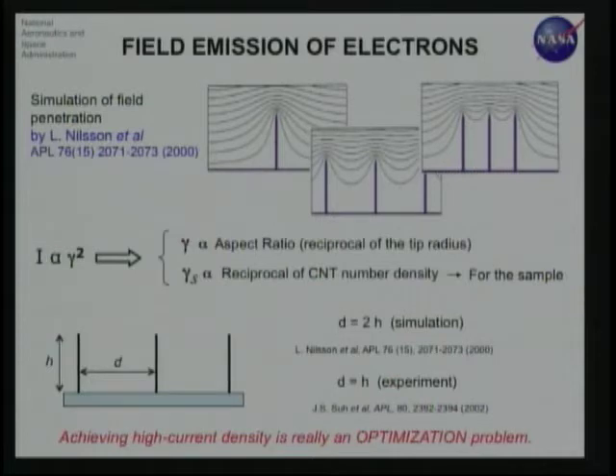And that is done by different ways. One of the ways identified is if you keep the distance between two consecutive emitters to be twice the height of the emitter itself, then you can get a pretty good optimum density and reduce the field electrostatic screening. But experimentally, there have been groups that have shown that it really needs to be a 1-to-1 ratio. So there is a range of opinions and proven results.